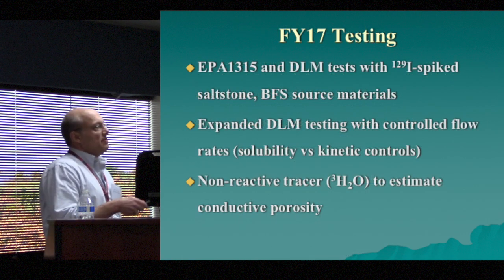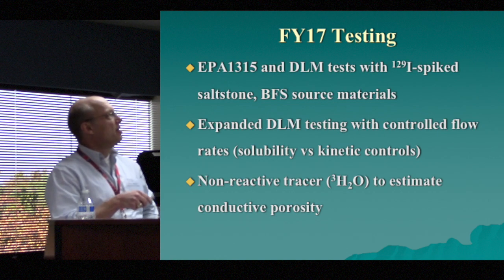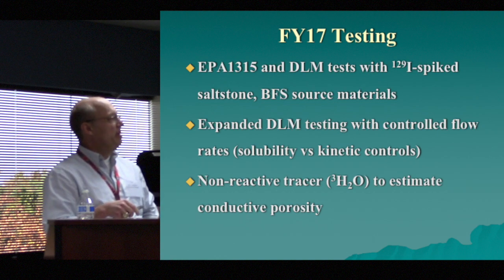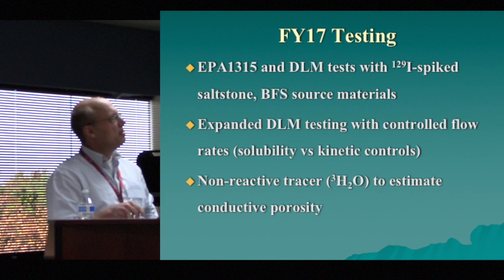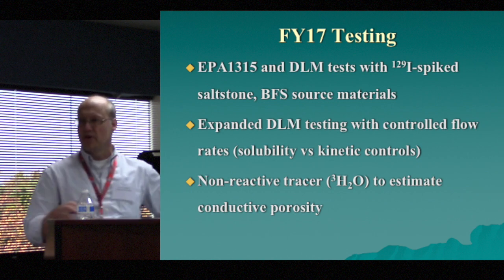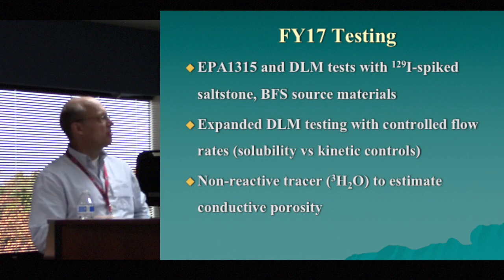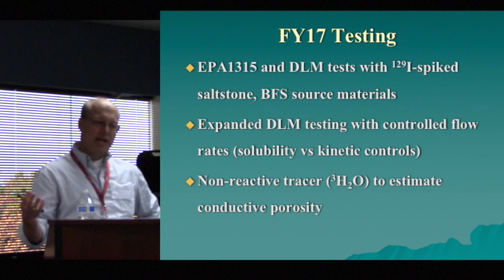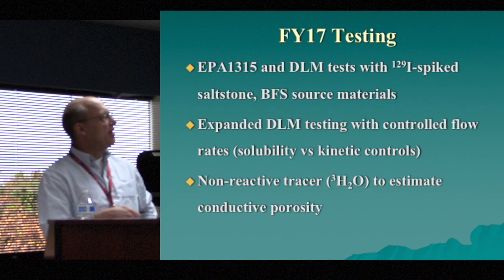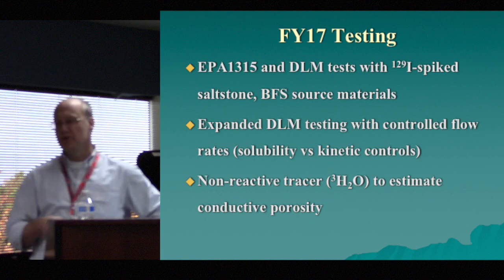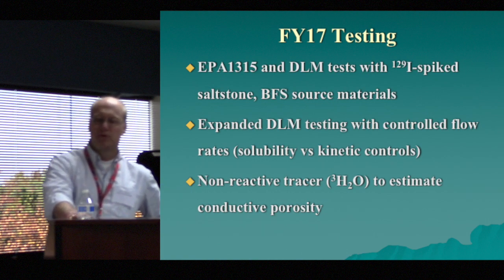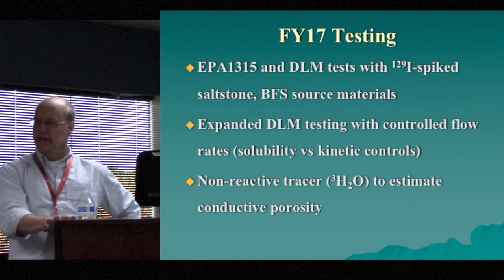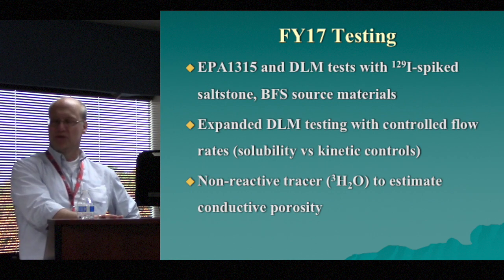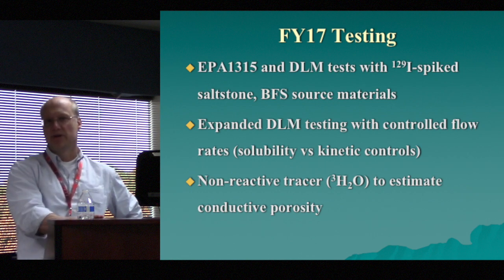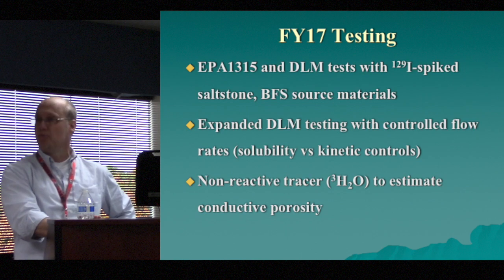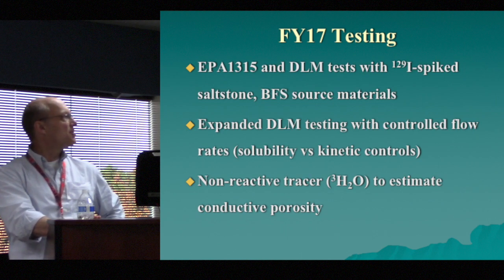So for FY17, we're going to go back and do more EPA1315 and DLM tests with the iodine-129 spiked saltstone this time, because we don't have a lot of iodine-129 samples or data. We're looking at these blast furnace slag source materials. We've got 3 or 4 different samples from Lehigh, to see if that is just a one-off sample or if they actually consistently have a much higher reduction capacity than what we had in the past.